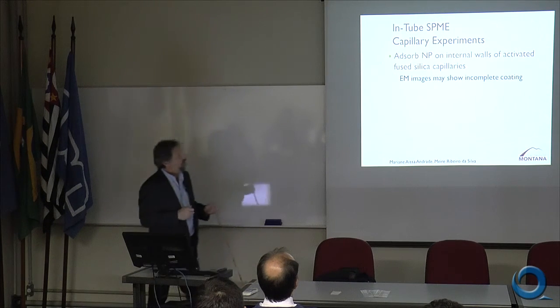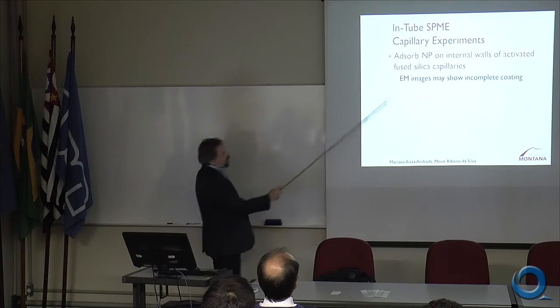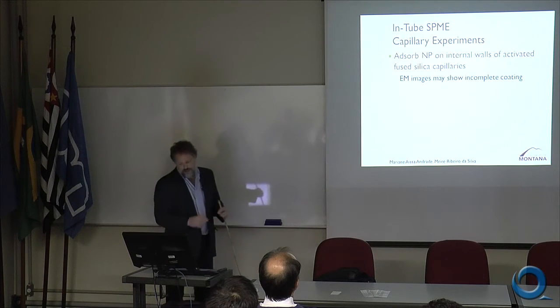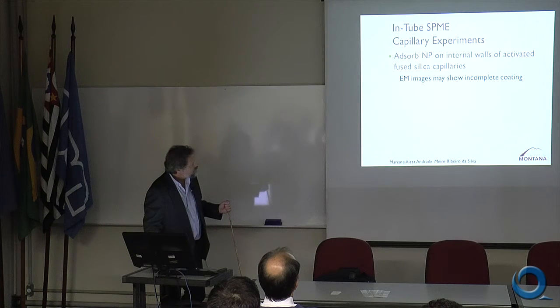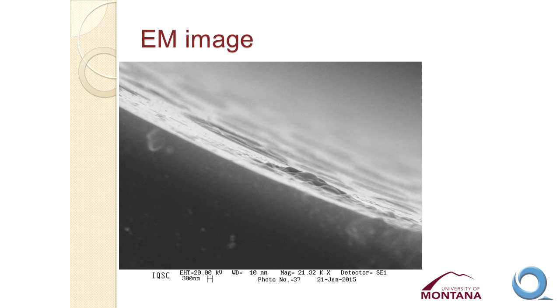solid phase microextraction. So we were able to get some electron microscopy done on the nanoparticles on the inside of these silica capillaries. And it takes a little bit of imagination, but if you compare this image to one for an uncoated silica capillary, the difference is these discs adsorbed onto the surface.